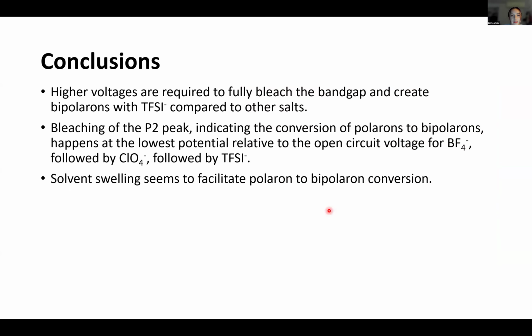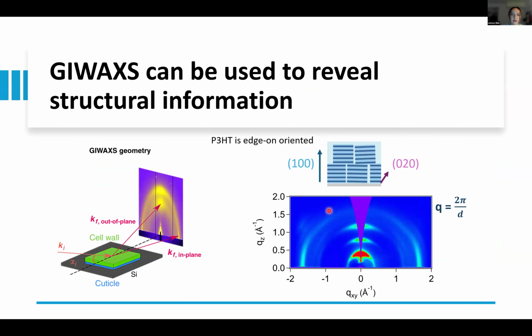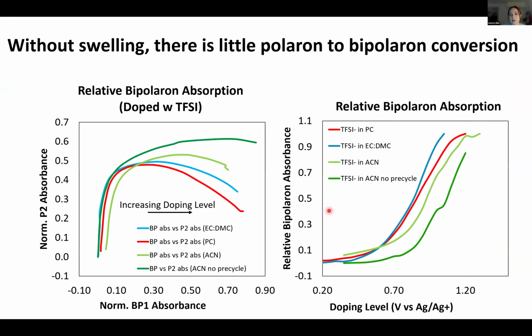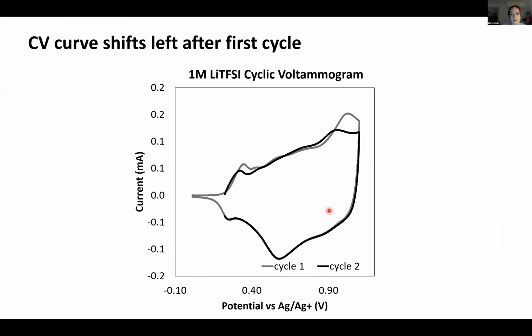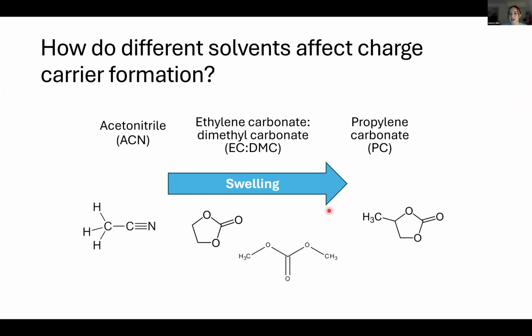Yeah. So these three solvents, I'll go back to that slide. These three solvents were ones that we had previous data on from our collaborators, and we had swelling data on them as well. So I was interested in looking at them because we had quantified the swelling previously. But I have also thought about the dielectric constant and how that is going to influence it, because these three also have various dielectric constants, but it seems that the trend is following this swelling effect rather than the dielectric constant. So I think that the swelling is having a greater impact here. But yeah, because we had quantified these before.